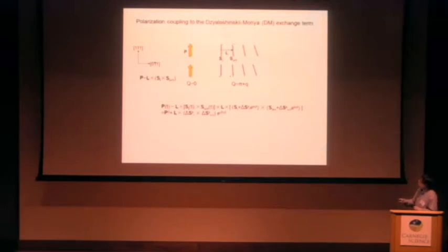And this term actually comes to be a static term, P0, which is the original term, plus a fluctuating term. And the fluctuating term, we can see, is actually a second-order effect. It only comes from the two spin fluctuation term. And if we think about the direction of this fluctuating term, we can see the top row, the direction of the fluctuating polar mode actually comes along the positive one-one-zero direction. The bottom row, if we do this cross product, it actually also gives a positive one-one-zero fluctuating term.